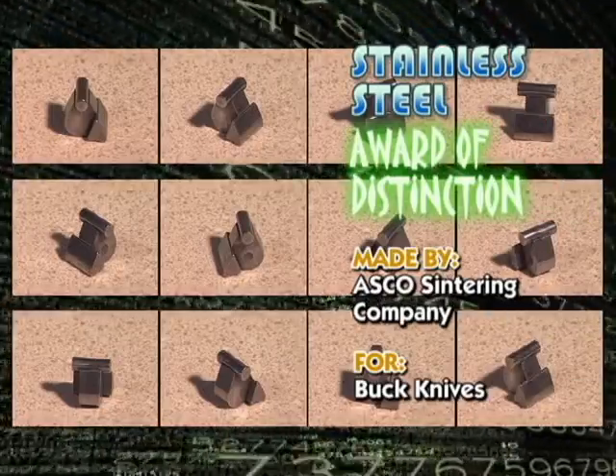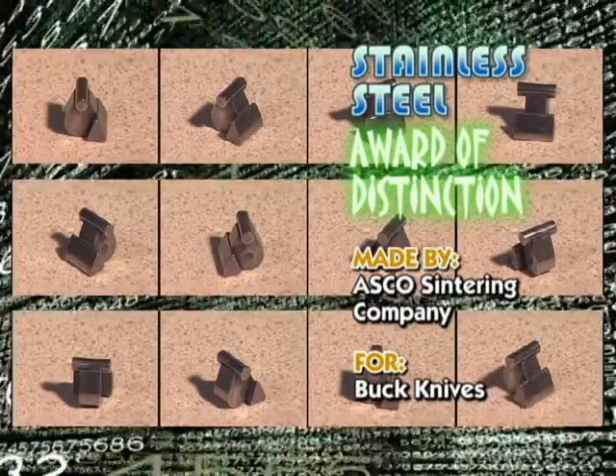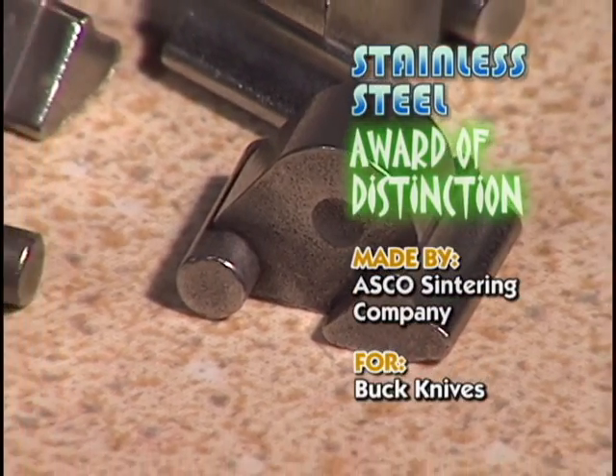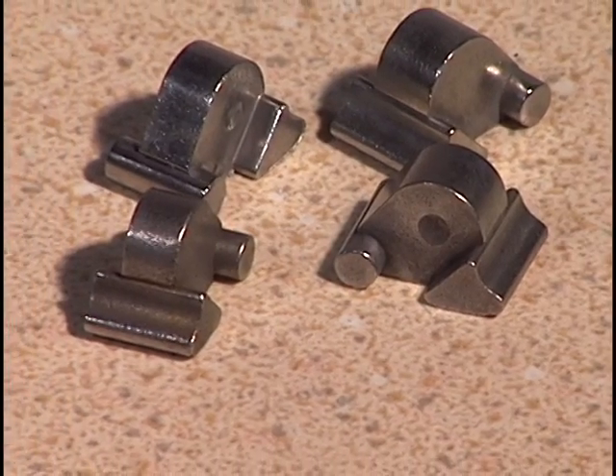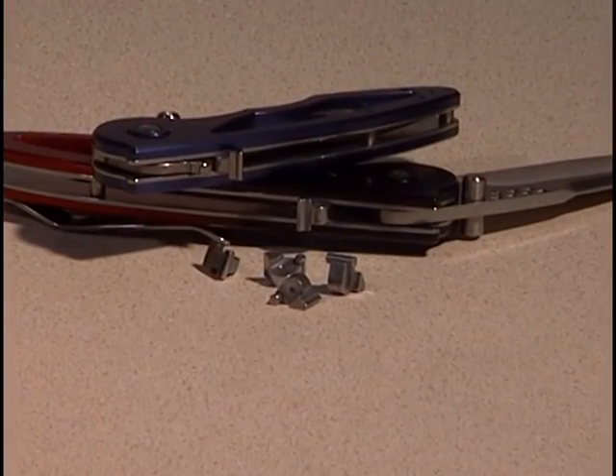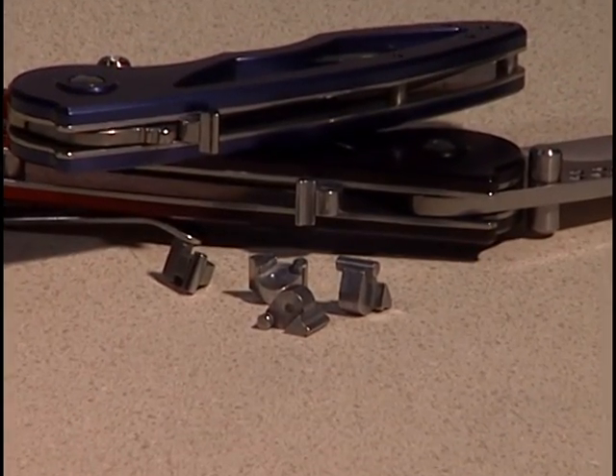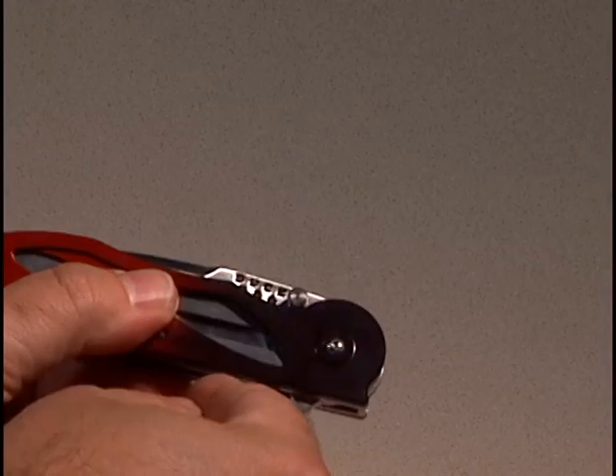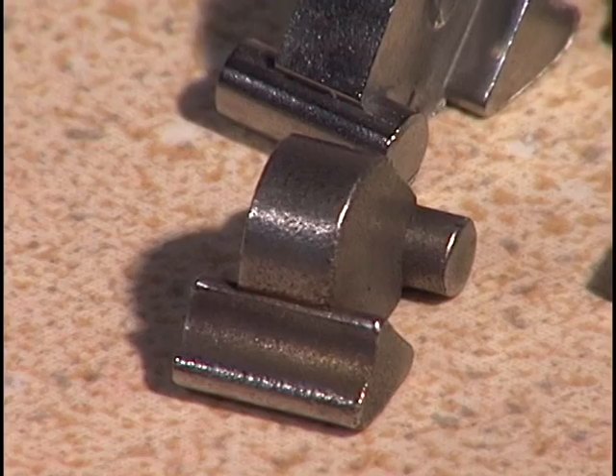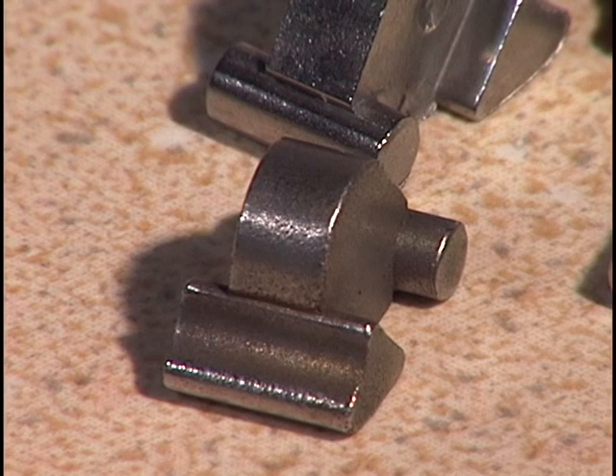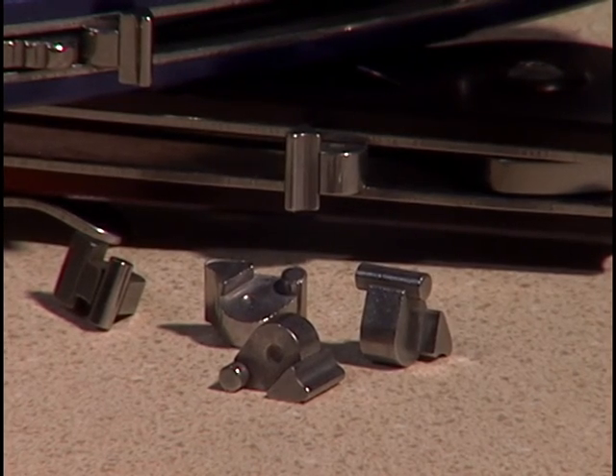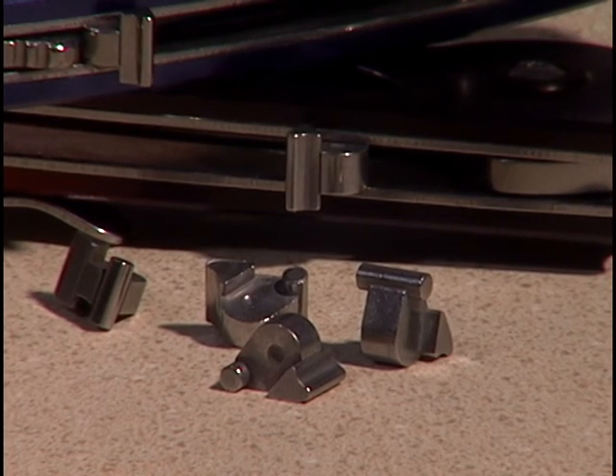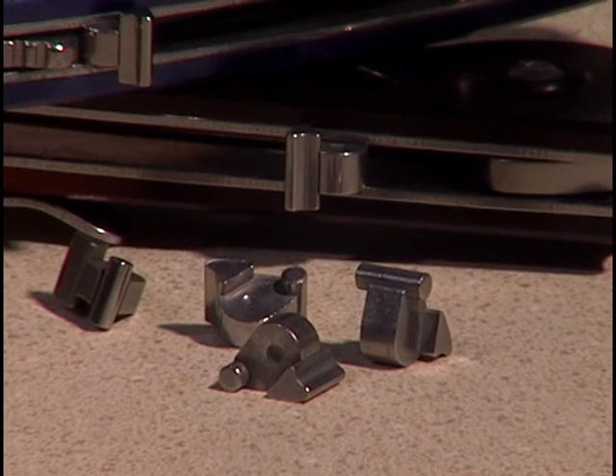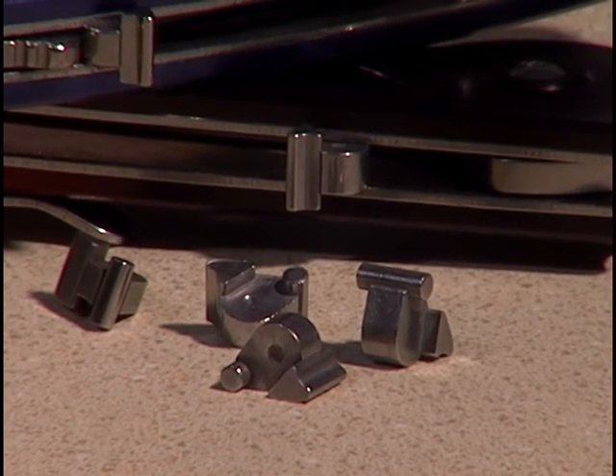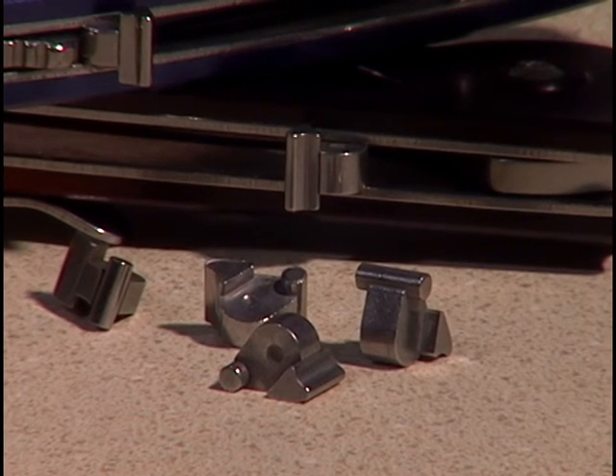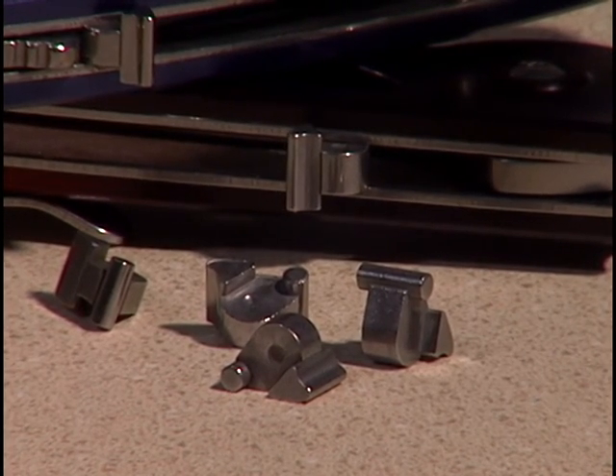ASCO Sintering Company won the award of distinction in the stainless steel category for a safety cam made for Buck knives. The cam operates in several models of Buck's new ASAP one-handed quick-release technology for opening the knife blade. The blade cannot open until the safety cam has been released. The 410 stainless steel part reflects an innovative tooling design to form its complex net shape. It is made to a density of 6.5 grams per cubic centimeter and has an ultimate tensile strength of 105,000 psi. Its yield strength is 90,000 psi and hardness is 23 HRC.